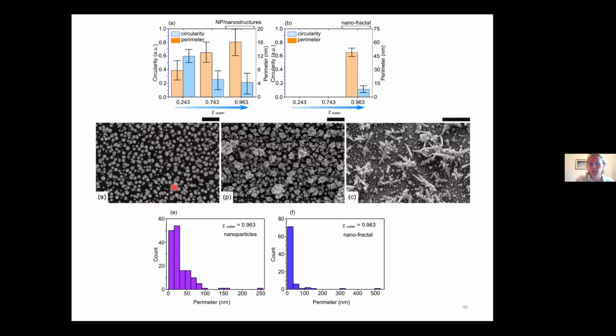And then this is just, we really let the system grow. I think this is a 300 seconds growth. At this point, everything was too thick to even do transmission electron microscopy on, so we had to resort to scanning. But you can see quite nicely, organic rich to water rich over here. Very different morphology that you're getting. So you can imagine, in things where you don't want dendrites growing, in lithium battery chemistry, you can see that just playing with the solvent contribution is completely changing the morphology of what you've got.